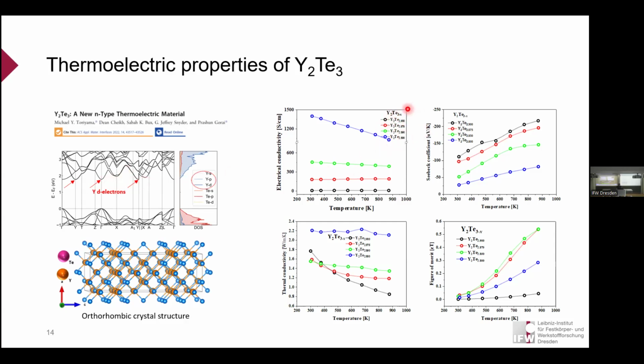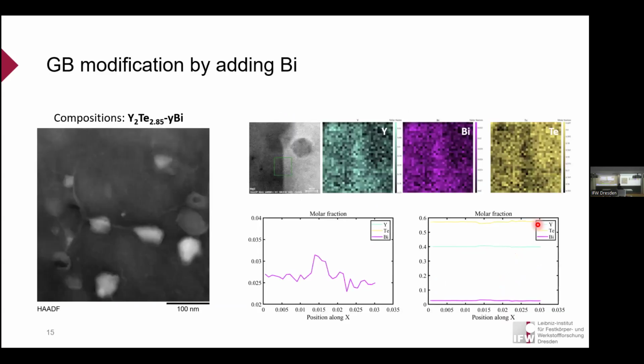And what we did is that if we decrease the nominal amount of tellurium, we could effectively enhance the electrical conductivity. Meanwhile, it corresponds to a decrease of the Seebeck coefficient. At the end of the day, we could see that the material has a ZT around 0.55, which is a decent material, but not very impressive. So then we can ask the question, what could grain boundary modification do to the properties of this material? And what we did is that we added some bismuth to the nominal composition.